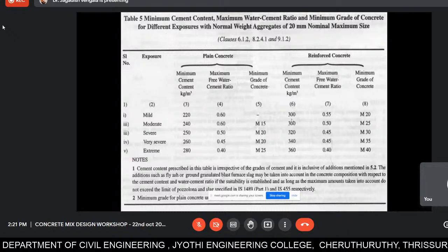Suppose you are in a coastal region, whether it is Mangalore or Machilipatnam or any other, or Mumbai, the coastal exposure condition, either it is severe or it comes as very severe. It depends on the element also. So for coastal, the exposure condition is say severe, then you are going for the reinforced concrete structure. For severe exposure condition, the minimum grade of concrete you have to go for is M30. When you're going for the M30 grade of concrete, the minimum cement content you have to use is 320 kg per cubic meter. And the maximum water cement ratio you have to limit at 0.45 for the severe exposure condition.